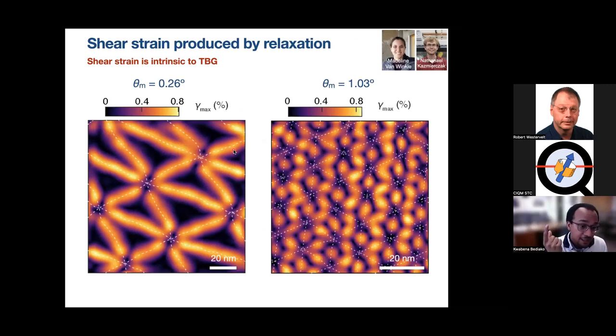Now, because we have these vector valid displacement fields, we can go a step further. We can directly measure and extract information about the strain, because it turns out that from infinitesimal strain theory, if you take the gradient of a displacement field, you get the strain. And so for all our samples where we have these displacement fields that we measure from Bragg interferometry, we can measure the shear strain, and there are a number of ways to represent the strain, different tensor rotations. This is a way of visualizing it isotropically. And you see that the strain is substantial both at small angles and approaching the magic angle region. And it is all localized basically in these saddle point regions. So that's the first thing that we learn.